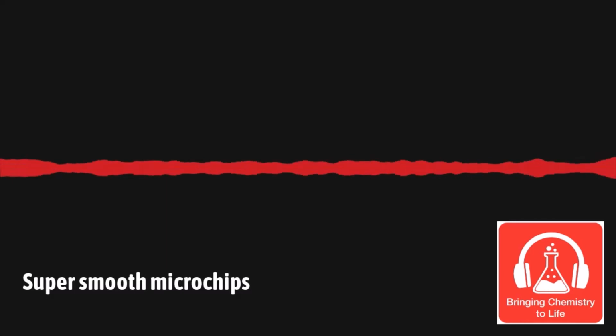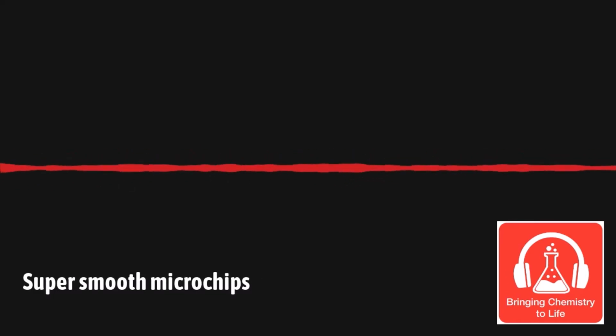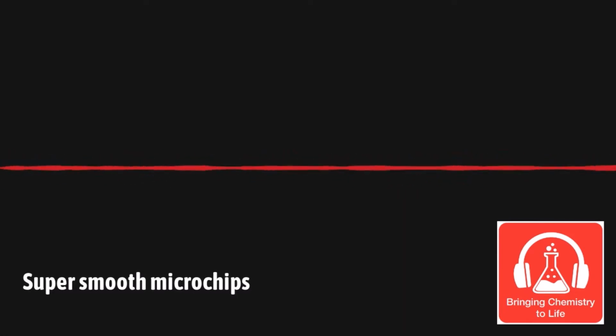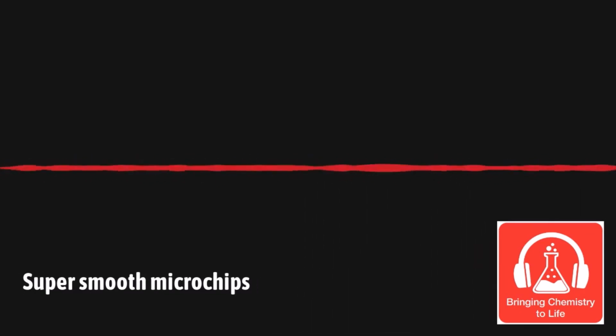So if you think about the percentage solids we use, the particle size, that particle distribution, that all drives that mechanical piece which I'm talking about. And that chemical piece is namely we're thinking about reactivity on that surface. Also adding different chemistries to control reactivity of the particle, stability, and also removal selectivities of the films.